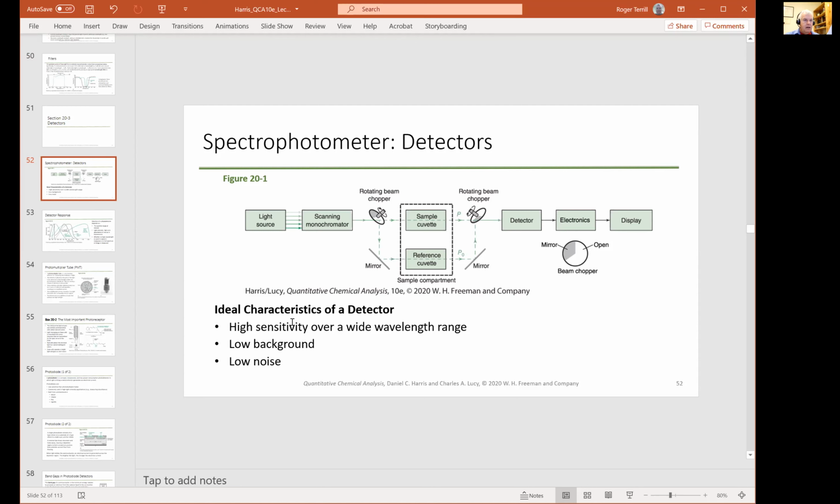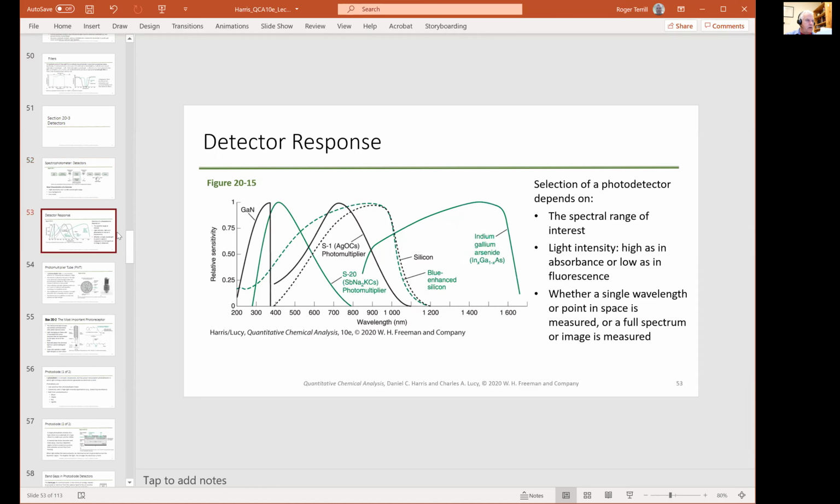Let us then see what types of detectors are available. These are the transducer type. The transducer type can be a semiconductor like gallium nitride, which sees only in the ultraviolet, or indium gallium arsenide, which sees in the near infrared, or silicon, or any other variety of materials, each of which is designed to liberate charge when a photon hits it, right?